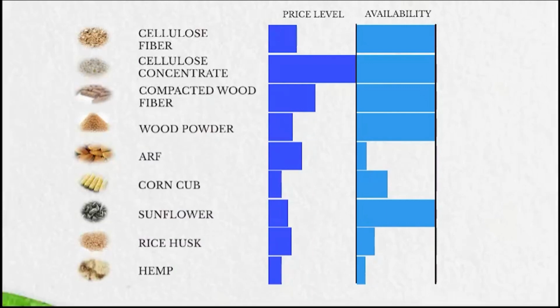The physical properties can also be modified with so-called hybrid composites, which contain mineral-based fillers in addition to polymer and natural fillers. In general, it can be said that compounds containing natural fillers have a brownish tint. Some compounds with fillers can be colored well, but others less so. The following figures show some measurement results. The same copolymer polypropylene was used as the base polymer. The amount of filler was 30% in all cases.